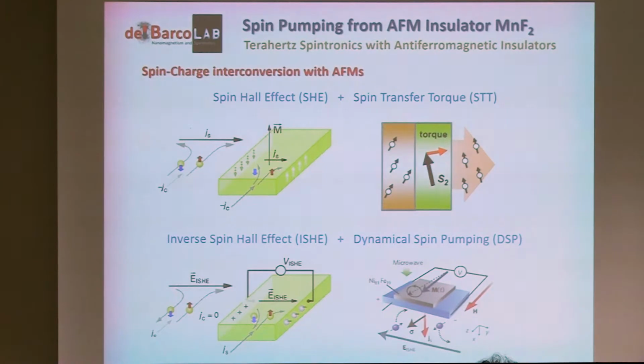So basically now you don't have polarized current getting into a ferromagnet exerting a torque. Now you have a ferromagnet, in this case, precessing coherently and pumping spins in every cycle, one angular momentum, into an adjacent metal and generating spin current perpendicular to the interface. If you employ the inverse spin Hall effect, reciprocal to the spin Hall effect, you can interconvert that spin current into charge current in a way that it will always be orthogonal between each other. So the charge current will be orthogonal to the spin current and the polarization direction, right?